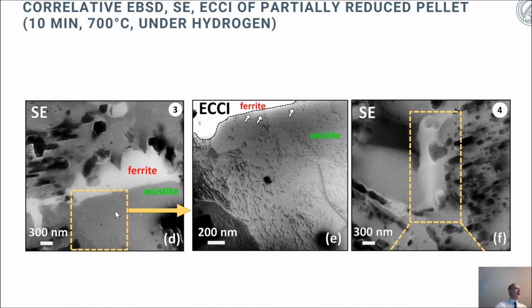This is shown here in a higher resolution, again at the interface between ferrite, which grows on top of the wüstite, and here is the wüstite. Again, the bright phase is the ferrite, and you see numerous types of pores and cracks that are building up everywhere around that growing ferrite. The other thing, which we will look into in a minute in detail, is at the direct interfaces. When you go to the ECCI contrast, which stands for electron channeling contrast imaging, you build up also certain dislocation and defect populations everywhere inside of the wüstite. That is what you see here.